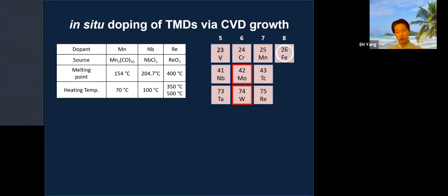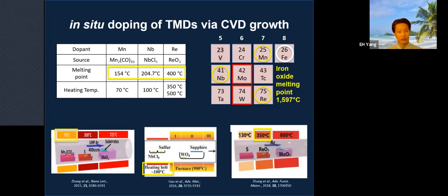Now, what we do is iron doping, and for that, we need to use iron oxide as a dopant source. But as you can see, the iron oxide melting point is nearly 1600 degrees C. That's very high. Compared to this, the reported dopants are manganese, niobium, and rhenium, and their melting points are 154, 204, and 400 degrees C. And naturally, to dope these while growing these materials, you have to put these dopant sources outside of the major heating zone. This doesn't work for us because we have to dope iron. So what do we do?